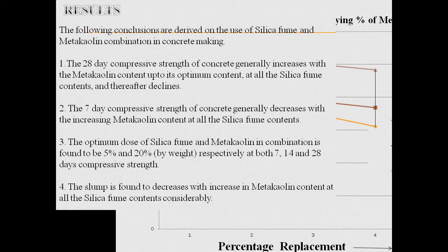From these we have obtained the results: the 28-day compressive strength of concrete generally increases with the metakaolin content up to its optimum content for all the silica fume contents, and thereafter it declines. The 7-day compressive strength of concrete generally decreases with increase in metakaolin content at all the silica fume contents. Thus, the optimum dosage should be 5% and 20%, that is the maximum strength. The slump is found to decrease with increase in metakaolin at all the silica fume contents.